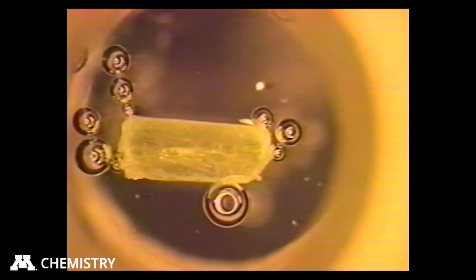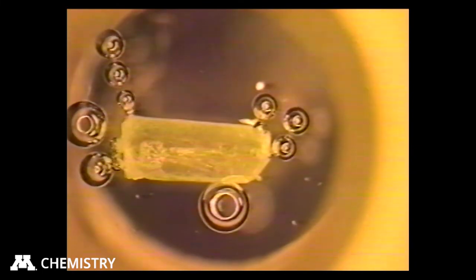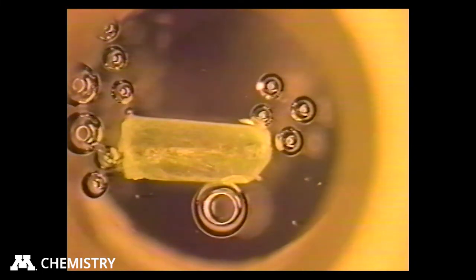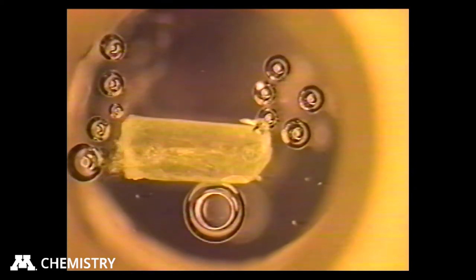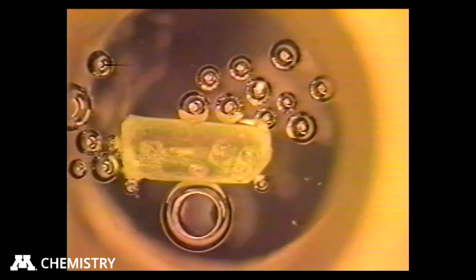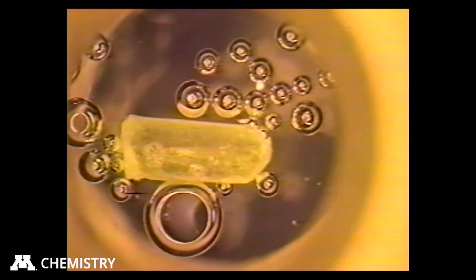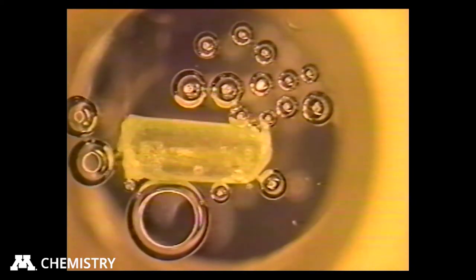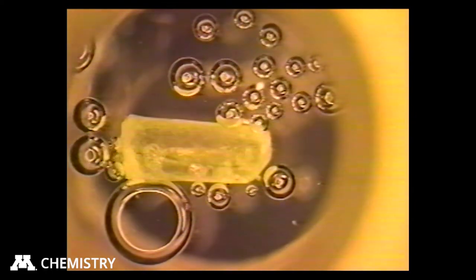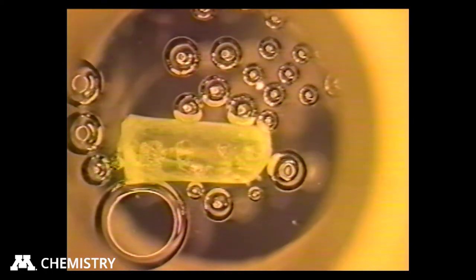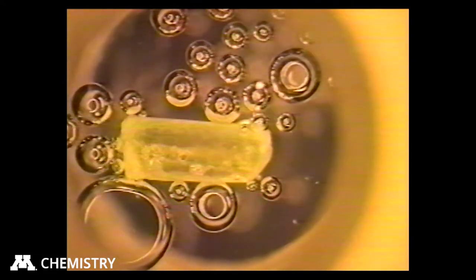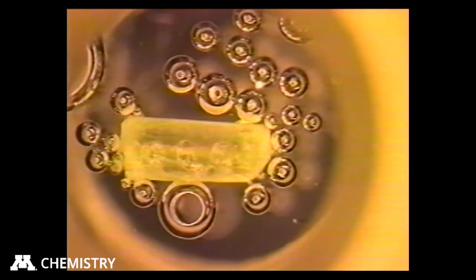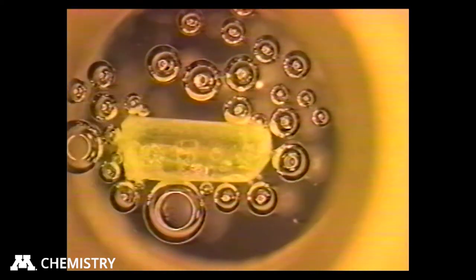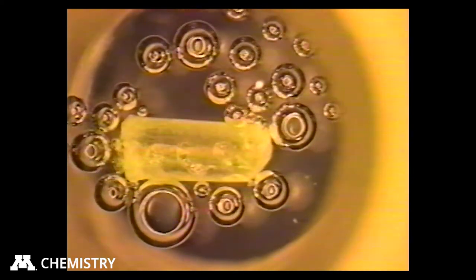All right, so you can see the crystal here, which is a dicarboxylic acid disodium salt. It has three water molecules in the crystal. And at this temperature, about 150 degrees, bubbles of water are just pouring off of the crystal. And you can see them being trapped in the silicone oil. If you watch carefully, you'll see that the crystal is starting to turn opaque at the same time, just like our dye crystal started to turn opaque as the reaction took place. This shows that there's some breakdown in the overall long-range order in the crystal, and you're developing little polycrystalline particles that scatter light.